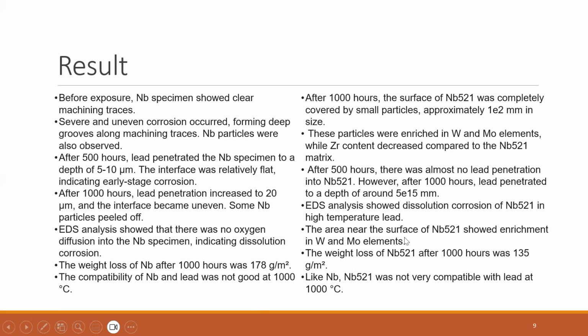EDS analysis shows dissolution corrosion of niobium alloy in high temperature lead, and the area near the surface of niobium alloy showed enrichment in W and molybdenum elements. The weight loss of niobium alloy after 1000 hours was 135 gram per meter squared. Like niobium, niobium alloy was not very compatible with lead at 1000 degrees Celsius.